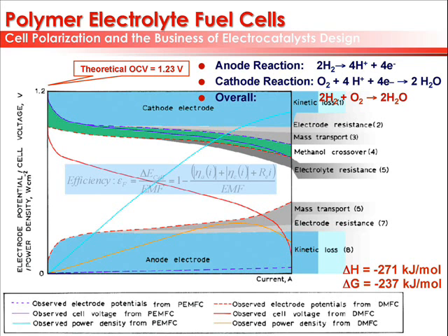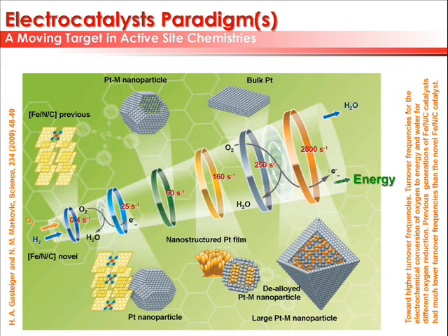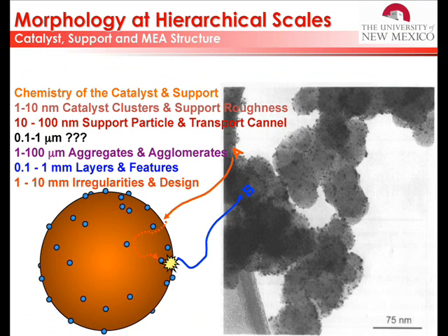And those losses, if you oxidize hydrogen, are predominantly concentrated on the cathode side. So they are all associated with reduction of oxygen. So any reasonable electrocatalysis lab has to have a program in making catalysts for oxygen reduction, because this is where most of the losses are. If you start oxidizing fuel different than hydrogen, you start incurring losses on the anode as well. That is why any reasonable electrochemical engineering laboratory has to have a program in anode oxidation catalysts if they are not for hydrogen. So essentially my laboratory does electrocatalysis of everything else except hydrogen.